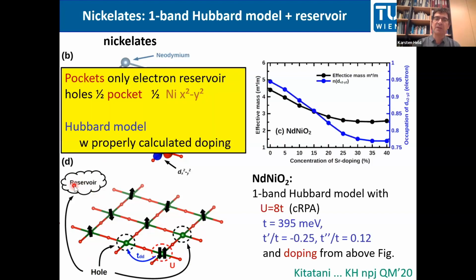And this translation of chemical doping to how much we dope this x squared minus y squared two-dimensional Hubbard model, that is what we can calculate in the full DFT plus DMFT calculation. It's the blue curve here. So even without strontium doping, you have something like 5% doping because of the electron pockets. And then about 50% of the holes go to the reservoir or the electron pocket, and 50% go to the Hubbard model. Please note that this is not a straight line. It has some curvature, and that will become important later on.